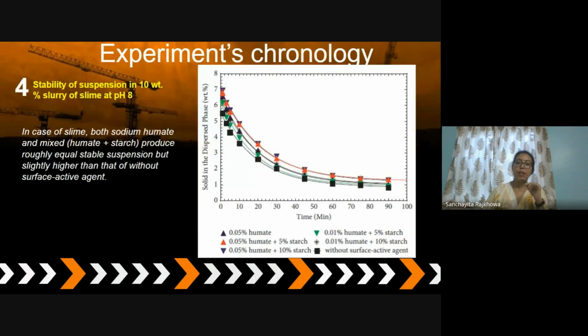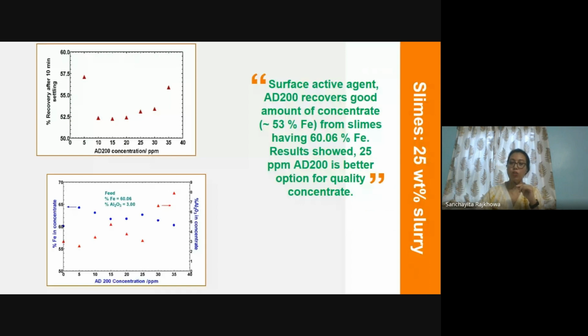Now, if we study the stability of suspension at 10% slurry, then in the case of slime, both humate as well as the humate and starch combination can produce almost comparable stable suspension. But if we go for the surfactant active agent, then it can do much better than humate and starch. Now, this particular slide says about the efficacy of our surfactant active agent, and it signifies that the hematite concentration from the slime slurry is reduced in the case of AD200, which is a better option than humate.